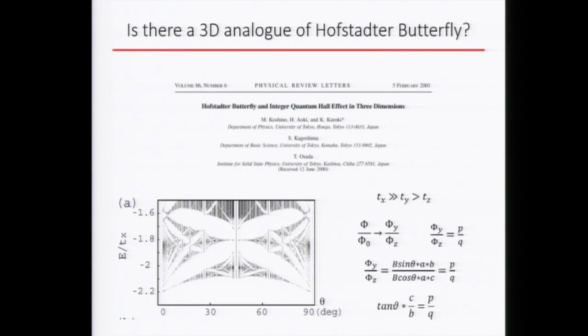In fact, around the year 2000, there's a theory paper by Koshino calculating the spectrum for a 3-dimensional Hofstadter butterfly, basically a tight binding model with a large magnetic field. In the condition that your dispersion along the x, y and z directions is highly anisotropic, meaning that the hopping along one direction is much stronger than in the other directions, then at a fixed magnetic field, when you rotate the angle, you can also create the same Hofstadter butterfly spectrum. And this commensurate field now corresponds to a commensurate angle. So instead of having, let's say, 1/3 of a flux quantum per unit cell, what you need is that the flux going through the AB lattice unit cell and the AC lattice unit cell has this commensurate ratio. So this is exactly the same condition under which we have observed this magic angle effect.